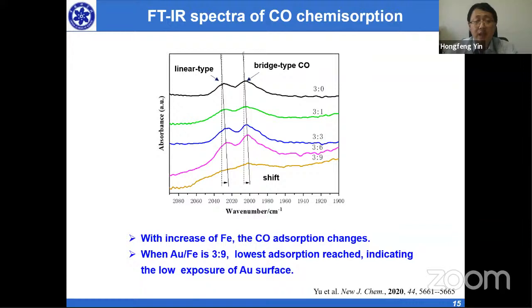Well, this is the FTIR. We can see that when there's no iron introduced, we have a linear type and a bridge type of carbon monoxide. But with the introduction of iron, the two peaks will merge, and finally become one peak. So that means the more iron introduced, the more the gold surface will be covered, so the exposure of the gold surface will be pretty low.